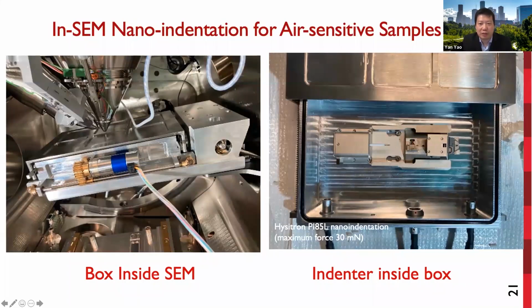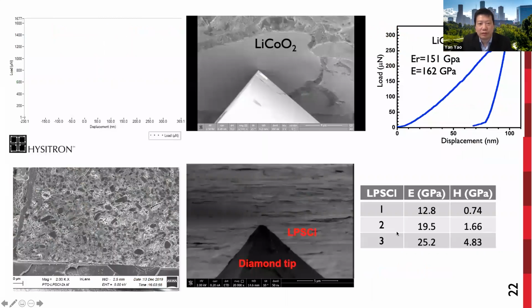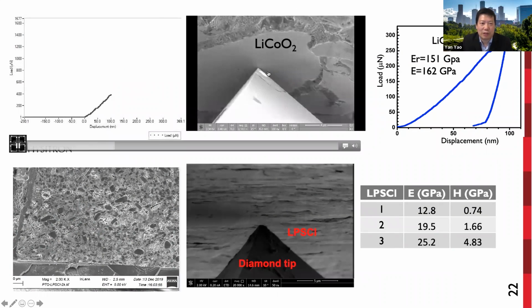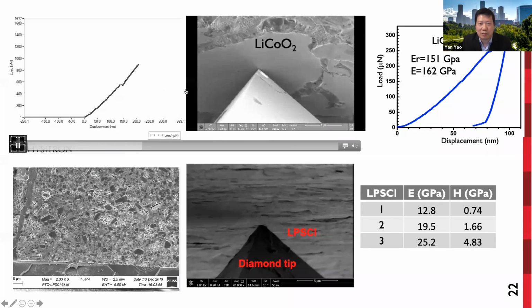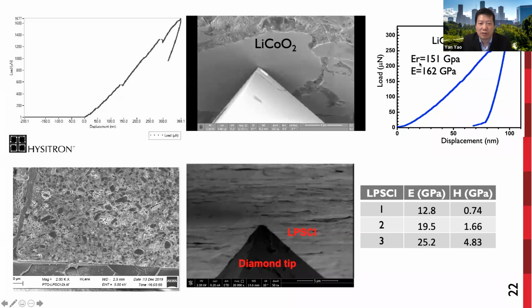So for mechanical characterization, a similar transfer vessel containing a nano-indenter has also been developed. This image shows the vessel inside the SEM; opening the cover can expose the tool we used for mechanical measurement. So this is a Hysitron nano-indenter. So mechanical tests can be performed by locating the diamond tip at different locations. When the tip is located on a lithium cobalt oxide particle, we can extract the modulus and hardness for the lithium cobalt oxide.